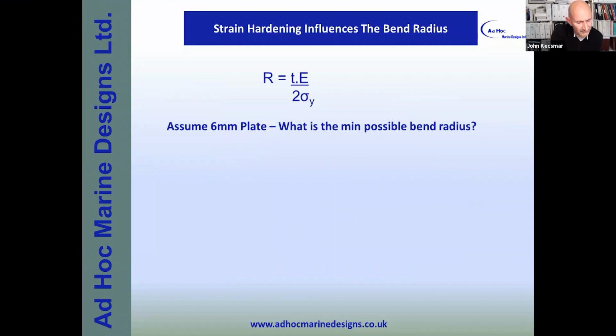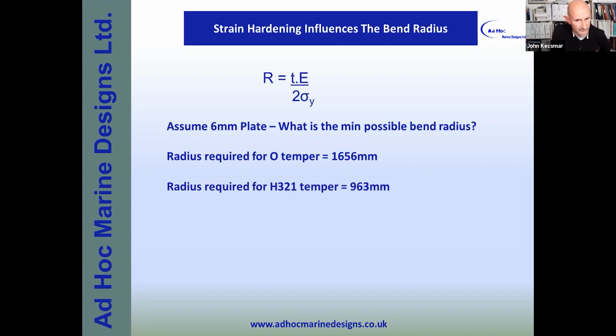It has implications in terms of fabricating the plate. We can quite easily work out what is the minimum bend radius possible by a very simple formula. It's just related to the yield stress and the thickness. So in this case, if we assume 6mm plate, the minimum bend radius is just over 1600 millimeters. The H321 is just over 900 millimeters. So that's quite an appreciable difference.